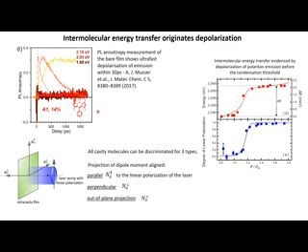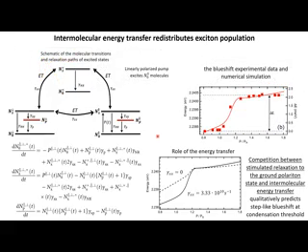It's just because there is a crosstalk between different molecules, and we show that indeed below condensation we have unpolarized light, but once we've built our condensate state, we observe a very high degree of polarization of our system, and this is accompanied by a jump-like blueshift in the system. To quantitatively describe nonlinearity of condensates, we developed a phenomenology based on three types of molecules: aligned parallel with linear laser polarization, perpendicular, and out of plane. Below threshold, if we excite, for instance, only these molecules, then due to the crosstalk, the energy transfer, they distribute population over all three types of molecules.